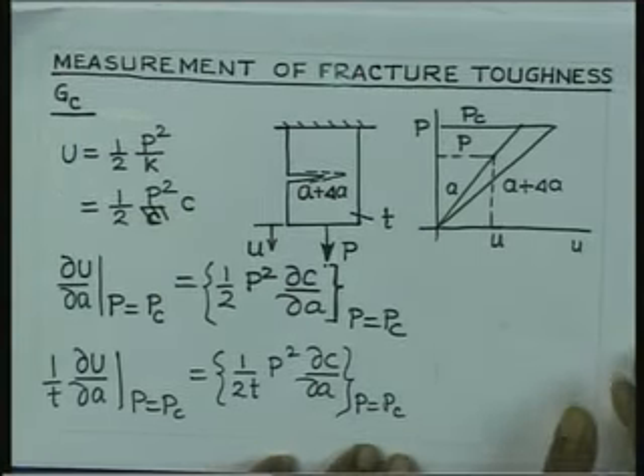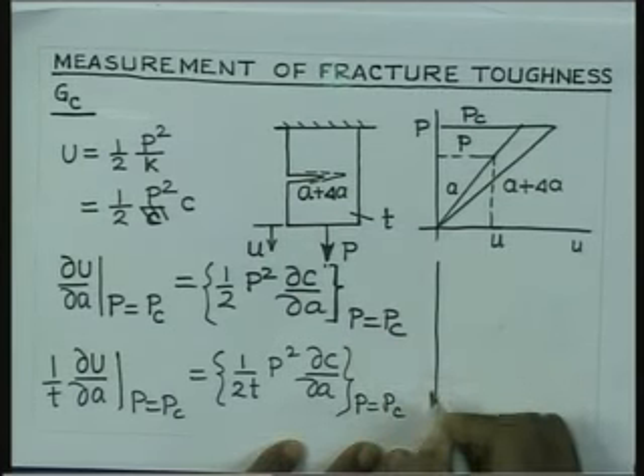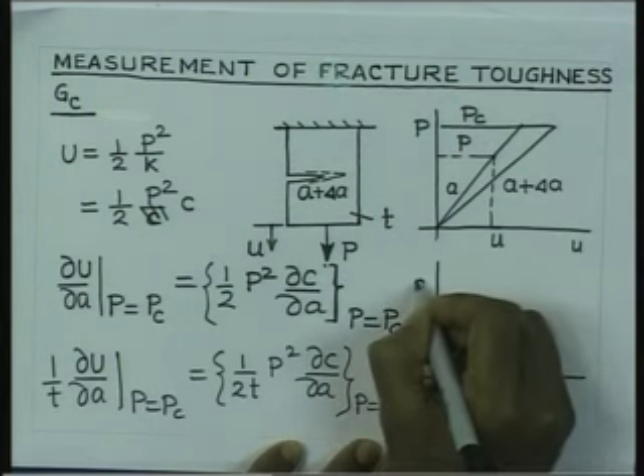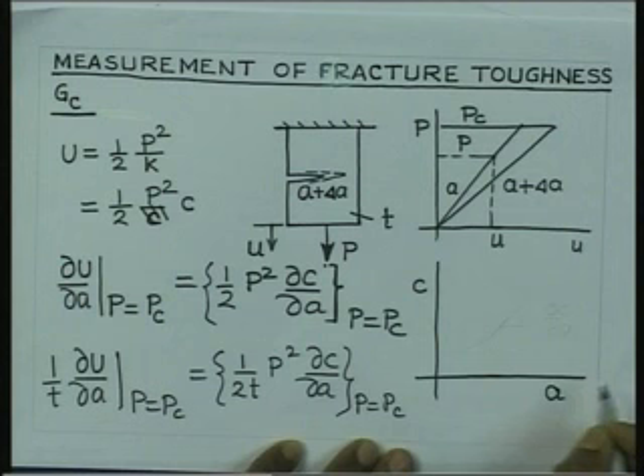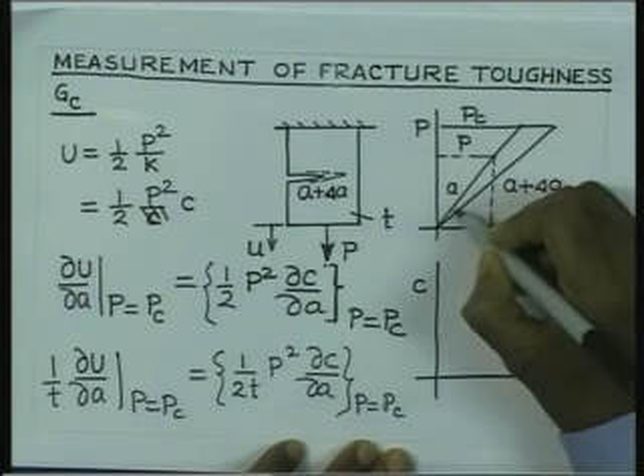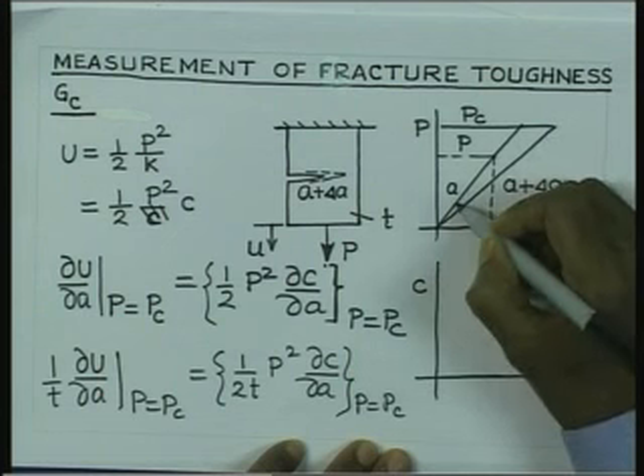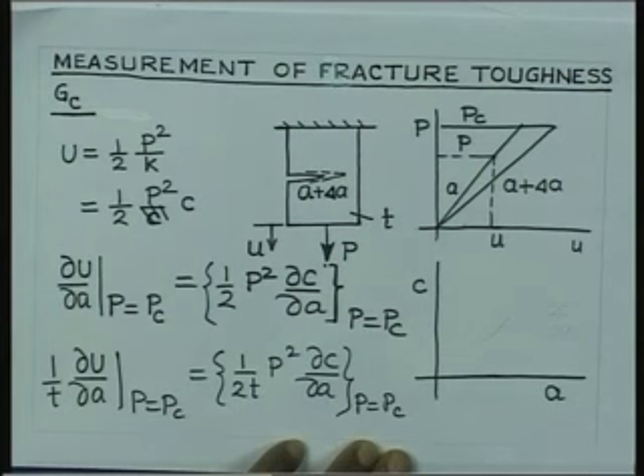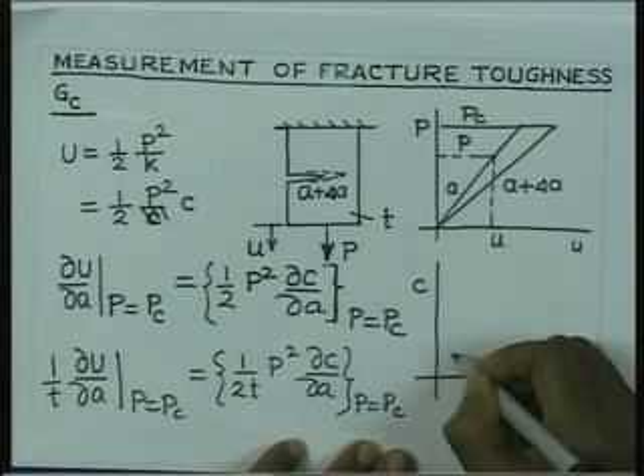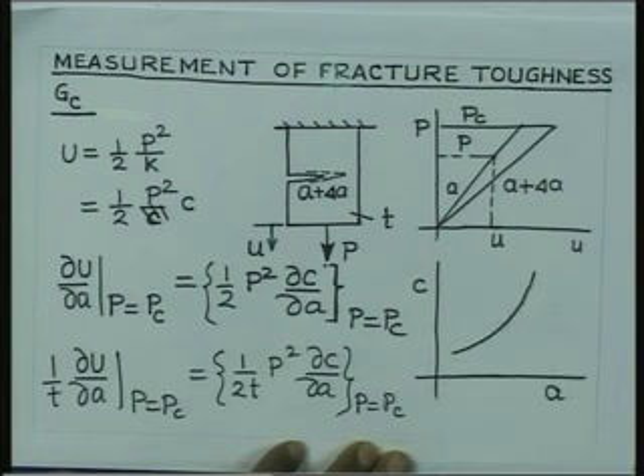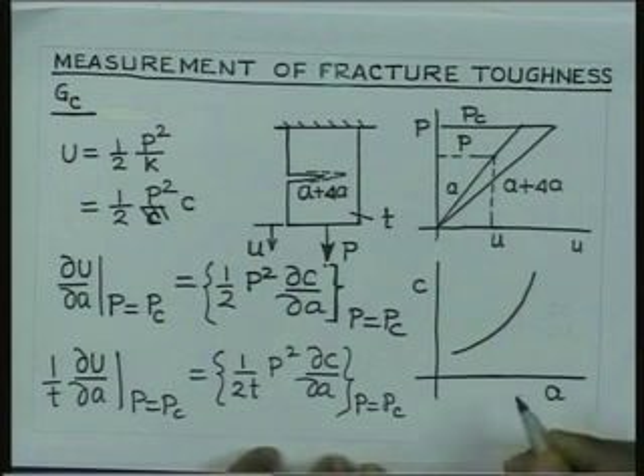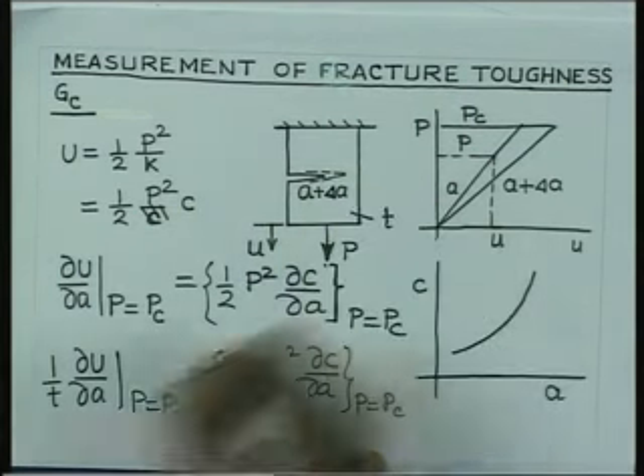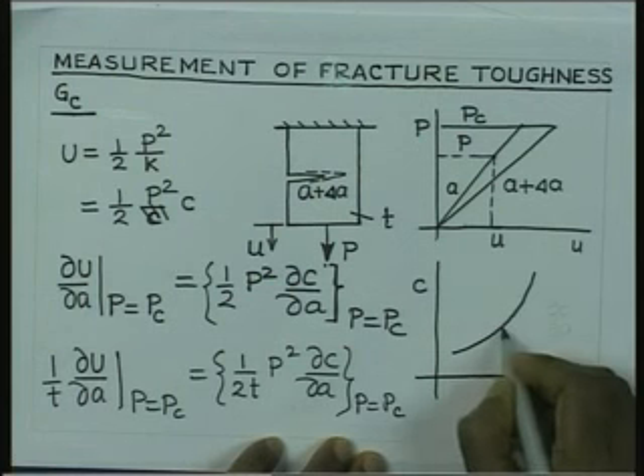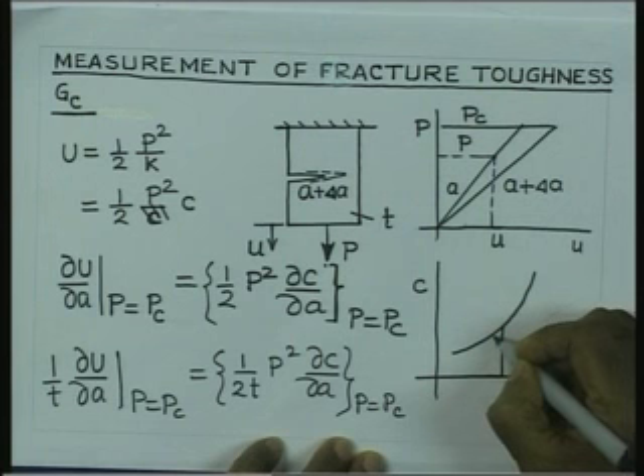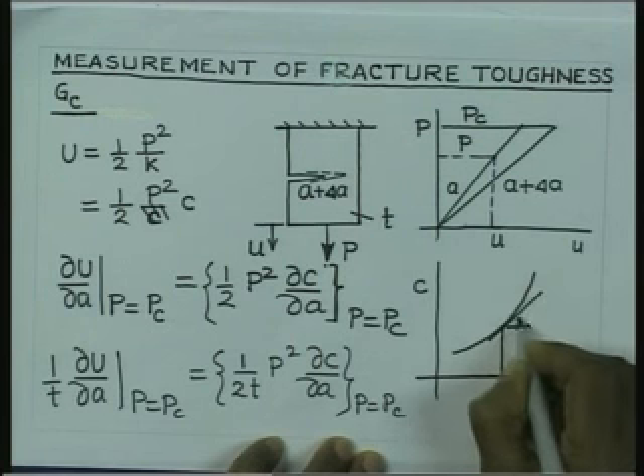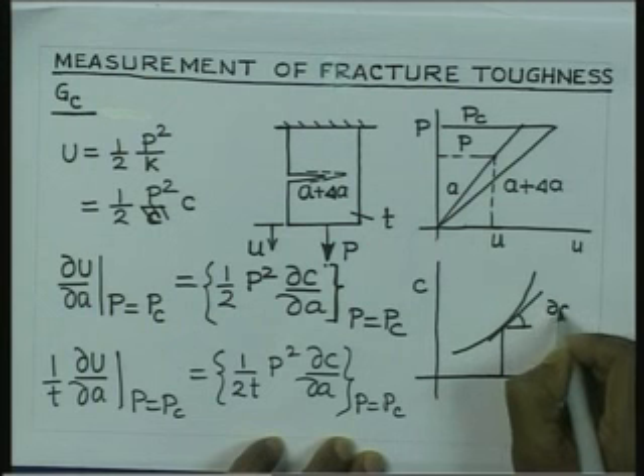If we can draw a curve showing the variation of this compliance for different crack lengths, so we can consider specimens of different crack lengths here, and if we find out the slope, that will give us stiffness, and the reciprocal of that will give us compliance. So, we can plot a curve, and this curve will look something like this. And if you are trying to do an experiment with a specific crack length A, you can find out the slope of the curve, delta C by delta A,